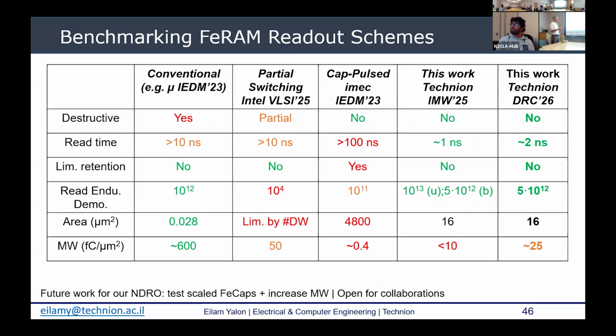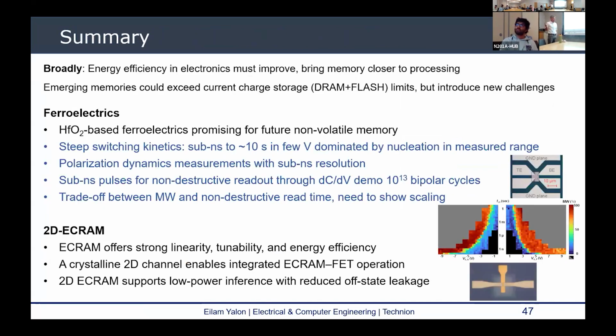What we still need to do is scale down the cell area from the same 4 micron structures that we had with the photolithography. And the memory window is not as large as you would get in the destructive readout, but you can accumulate the signal over a few cycles. So there is a trade-off between the time and the memory window, but it's not destructive, so it has, in principle, infinite endurance, and it's faster and lower energy than the destructive readout. So it's not an issue to accumulate a few signals. Yeah, that's what I wanted to share.